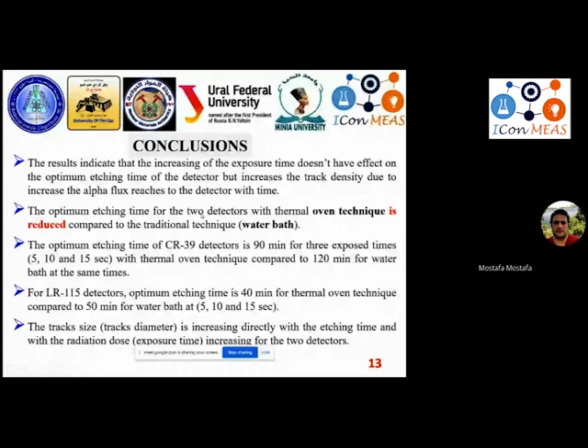Finally, we can reach the conclusions. The results indicate that the increase of the exposure time doesn't have an effect on the optimum etching time of the detector, but increases the track density due to the increase of alpha flux reaching the detector with time.